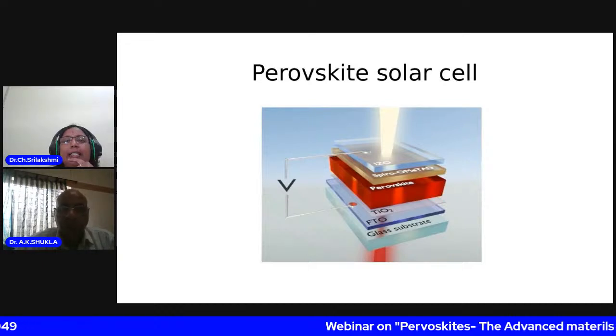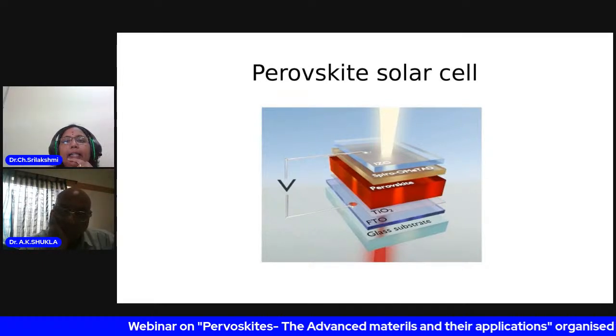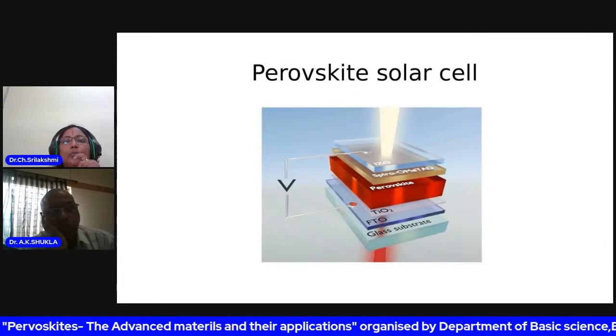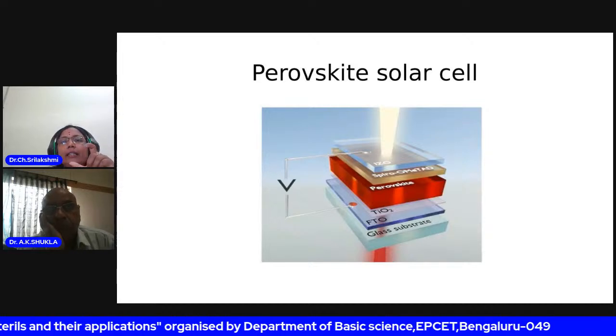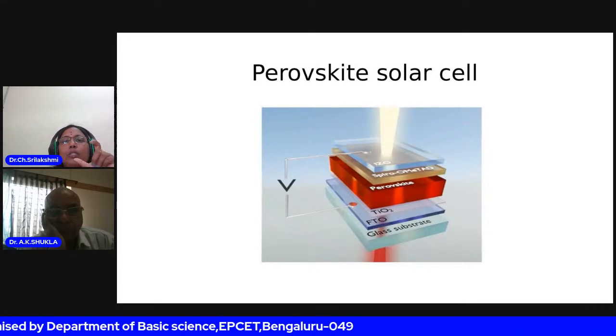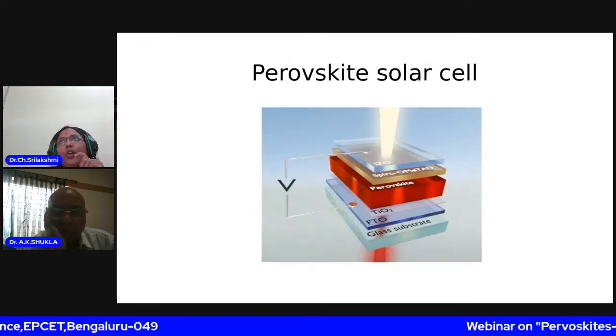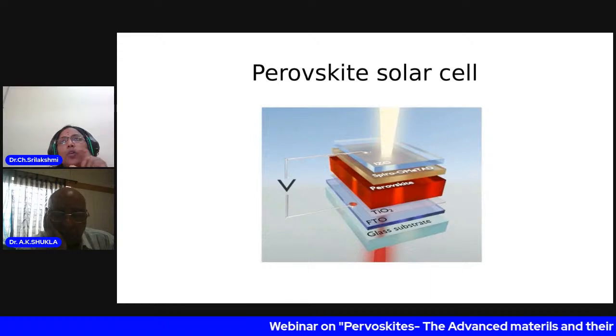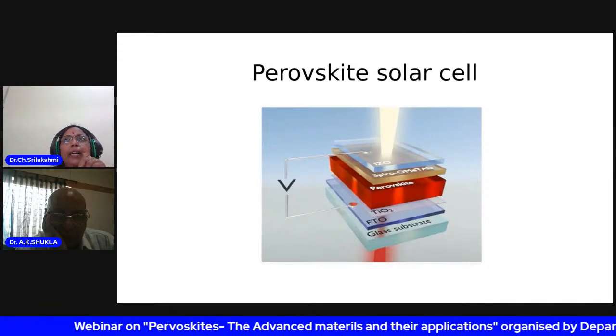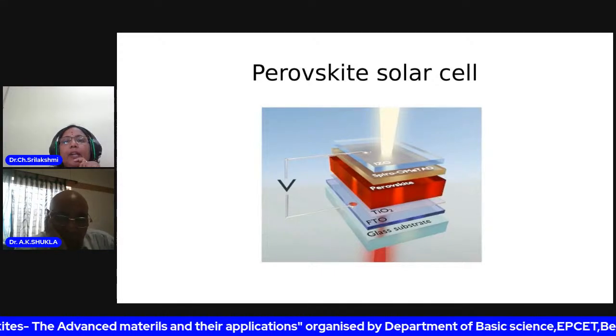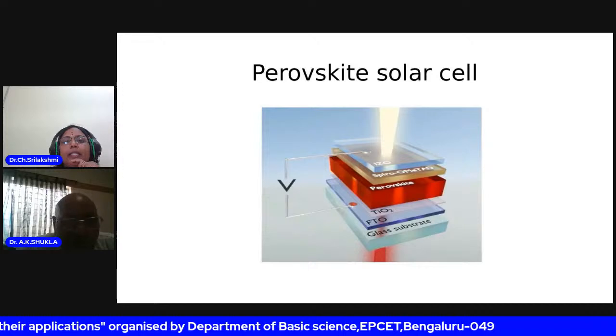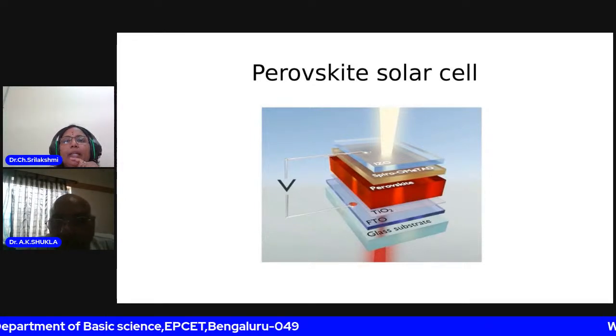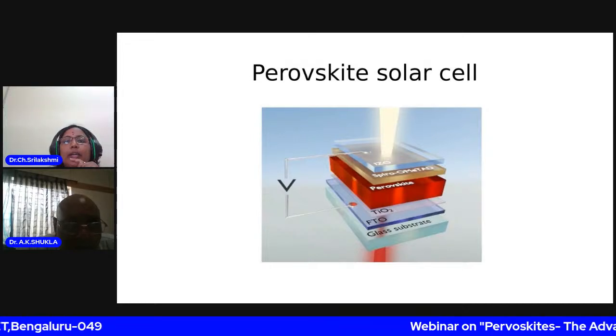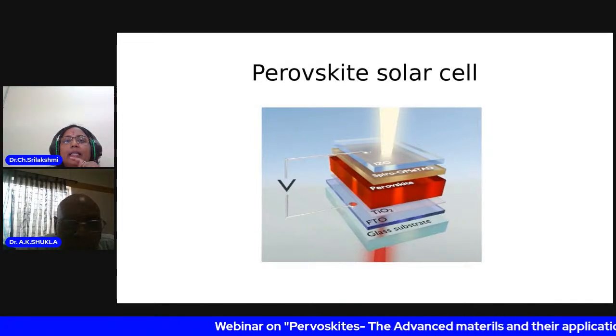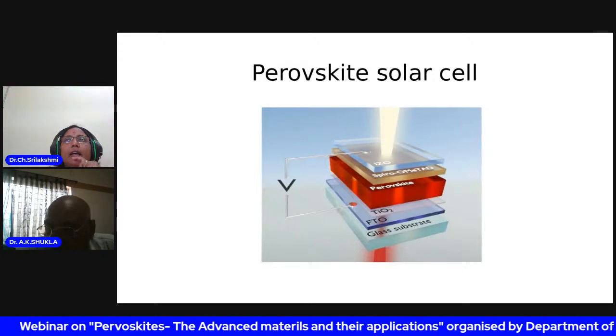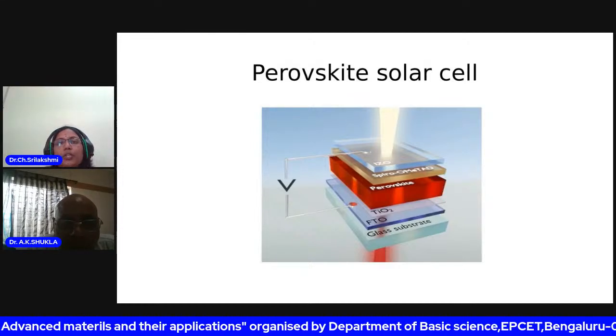The electrons and holes are created in the perovskite layer, and later the hole transport material and electron transport material such as TiO2 collect the holes and the electrons. Suppose here the ETM, electron transport layer, is TiO2. Because of the difference in the exciton binding energies, they can be separated efficiently by the perovskite layer, and electrons are collected by the titanium oxide layer, and the holes are collected by the hole transport material, and these are further collected by the electrode material here. So electrons are collected by the FTO material and holes by the electrode, and these two electrode materials are connected, and the photocurrent is generated in the outer circuit.